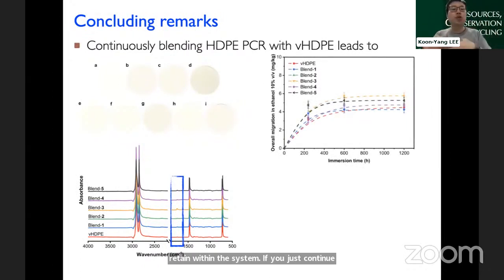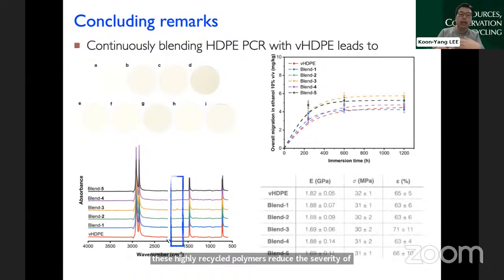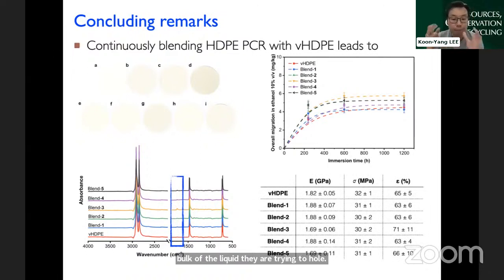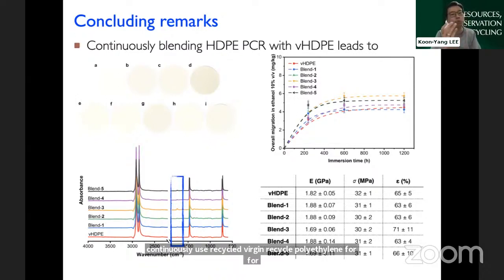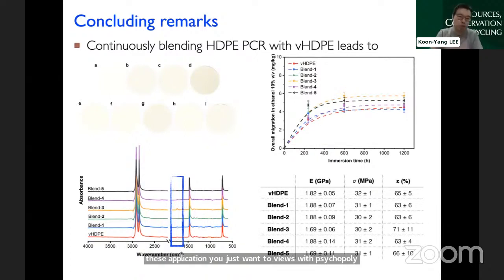You will have a slight issue with migration, but the fact that you're blending in virgin polymers with these highly recycled polymers reduces the severity of the migration of small molecular weight molecules into the bulk of the liquid they're trying to hold. And mechanically speaking, you do want to have that virgin polyethylene with your recycled polyethylene to maintain mechanical performance, such that it can be used in what it's designed to do. So you do not want to just continuously use recycled polyethylene for these applications. You want to blend recycled polyethylene with virgin polyethylene to achieve the mechanical performance that you initially designed for.